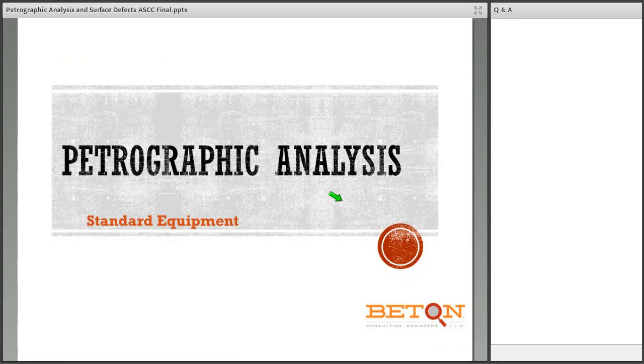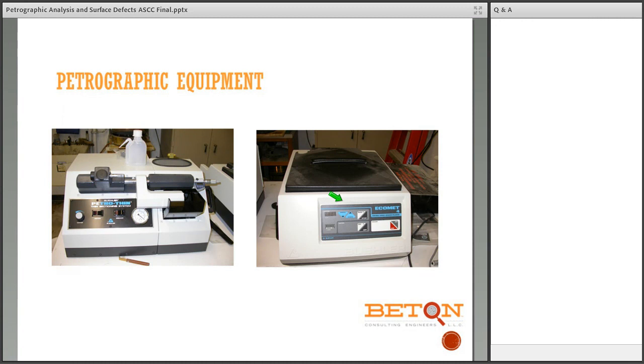Standard equipment that we use, basically, we've got some polishing equipment to polish hand specimens and to prepare the thin sections for making thin sections. This is a Petro thin, which is our equipment that we use for making thin sections. Basically, that involves cutting a rectangular billet out of the sample in an area of interest, cut it, polish it, epoxy impregnate it to stabilize the paste, allow that epoxy to cure, polish it again, and then glue it to a glass slide, and do final polishing with it until it's about 20 microns or less in thickness. Think about it, the human hair is probably 70 or 80 microns in diameter, depending on the individual.